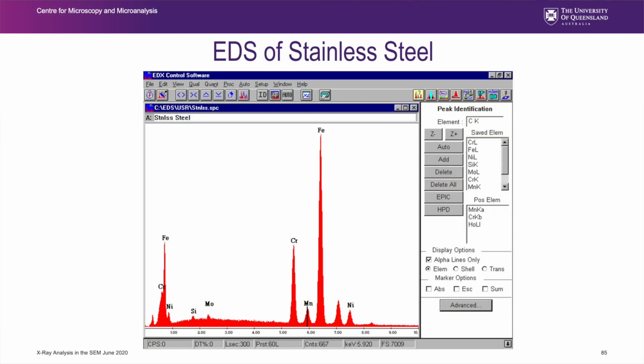So this is an EDS spectra of some stainless steel, and you can see I've got my iron peaks, my chrome peaks, manganese peaks, nickel peaks. On the right, these big peaks, around 5, 6, 7 keV, they are the chrome and iron K alpha. These ones down here are the chrome and iron L alpha peaks. You can see below 1 keV in energy, the spectrum becomes very crowded. This is the iron K alpha, this big one here, and this small one here is the iron K beta.